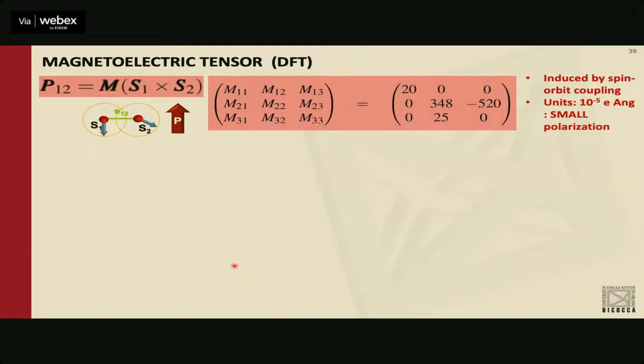Additional step. Given that you have a spin helix, is this ferroelectric? With this, we calculated basically the electric dipole that arises from two spins being non-collinear. So if I have two spins that are non-collinear, does it give rise to a dipole moment? This you can also estimate by first principles. You can estimate this kind of magnetoelectric tensor.